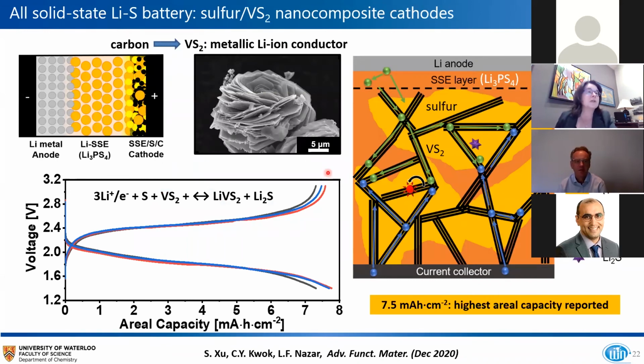So we've turned our attention first to solid state cells, and to try to make some impact in this field, we've turned away from the traditional, well, traditional being the last couple of years, lithium sulfur cell that uses carbon as the conductive additive in the cathode, to nanostructured vanadium disulfide. The reason for that is that VS2 is a metallic material with very high conductivity. And we can form this material in a very high surface area, nano flower structured morphology. This allows intimate contact of the VS2 with the sulfur. And the VS2 is not just a metallic conductor, but it's also a good ion conductor. So it acts as a vehicle to deliver both ions and electrons to the sulfur to trigger the conversion of sulfur to Li2S. And simultaneously, we get capacity from intercalation of lithium into the VS2. And so we end up with very high areal capacities, which, at least to our knowledge, are the highest that are reported, and stable cycling behavior.